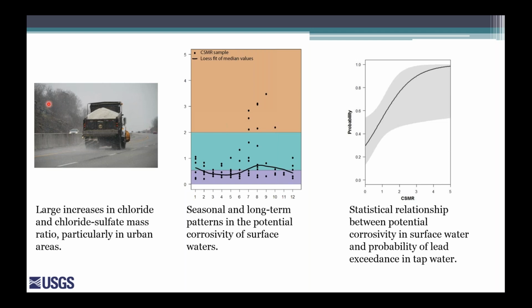They add it in the form of alum, so aluminum sulfate, and they add it as a coagulant. And some of the instances of lead contamination relating back to the chloride to sulfate mass ratio resulted from a change in the coagulant from alum to a chloride-based or aluminum-based coagulant that changed the chloride to sulfate mass ratio. And so, there is evidence that within these drinking water facilities that changing the chloride to sulfate mass ratio through a difference in the treatment wound up affecting the mobilization of lead within the distribution system. But I agree, that is a good question of why you don't add sulfate to drinking water facilities.